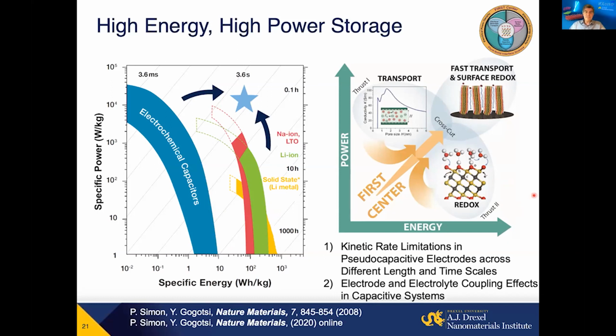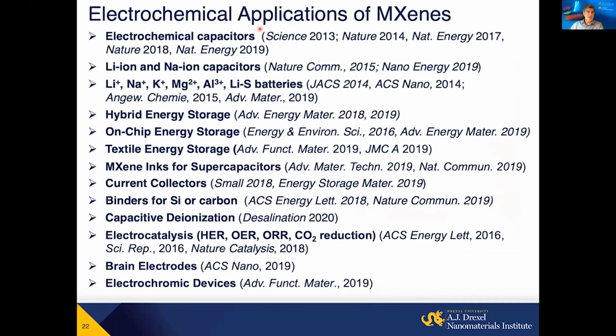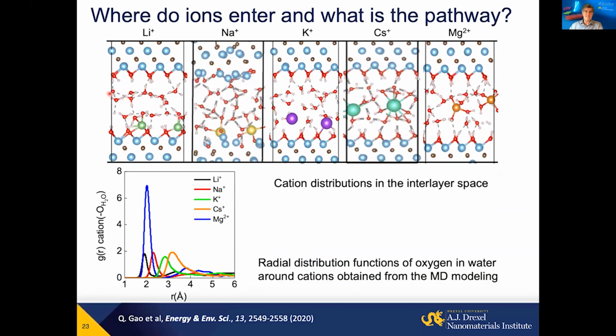If we have electronic conductivity, that can give us high rate, because basically charging a battery quickly simply means running high current through a battery. So you really need metallic materials that can also experience surface redox to have high energy, high density storage. And not surprisingly, MXenes have already been explored in a variety of energy storage applications. I have no time, of course, to talk about them, but they range from electrochemical capacitors to all kinds of batteries, metal ion capacitors, and also, what is important, passive elements. You may recall I showed you a 1 micron thin, very highly conducting and very strong film of MXene, which can potentially replace current collectors in many devices. And of course, if you make an MXene battery, you won't need conducting additives or binders.